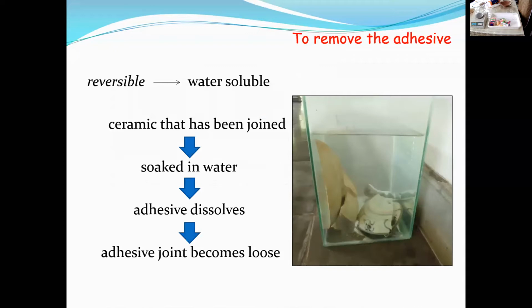Why we call this type adhesive as reversible? Because the adhesive, the natural adhesive that we use is water soluble. As we could see, if we immerse the ceramic in water, the adhesive will be dissolved in water. It will become loose and the joint parts will be detached. This shows the weakness of the material, but it could be an advantage of the material.